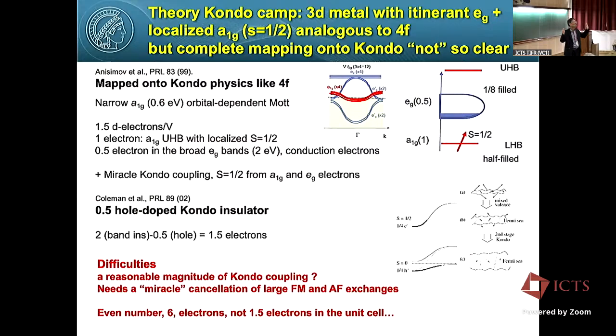And theoretically, there are 2 camps, the Kondo camp and the Mott camp. And in the early days, Anisimov said this compound can be mapped onto Kondo physics. And his reasoning is that this A1G band I showed is very narrow, like half an electron volt. And introducing a Coulomb U, it splits into a lower Hubbard and an upper Hubbard band. And the lower Hubbard contains one localized spin, or a half-integer moment. And the remaining 0.5 electron occupies the EG band. So you have conduction electrons and a localized moment due to the correlation effect on A1G. And he discussed that there could be a miracle Kondo coupling due to cancellation of ferromagnetic exchange and antiferromagnetic superexchange.